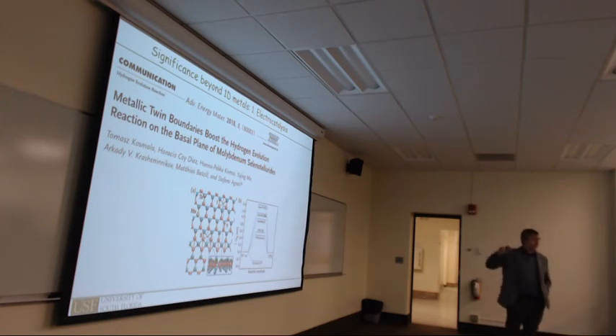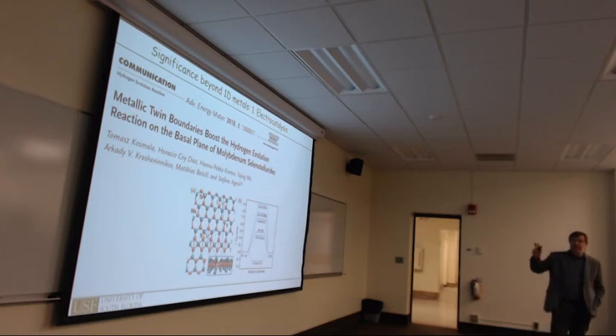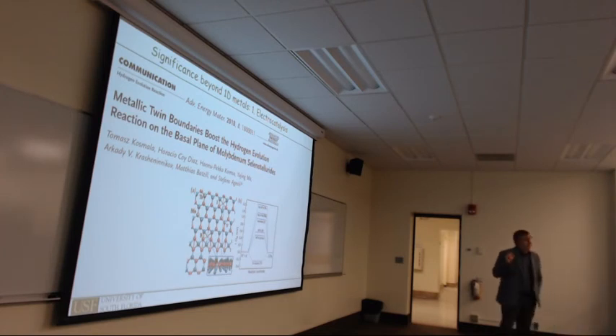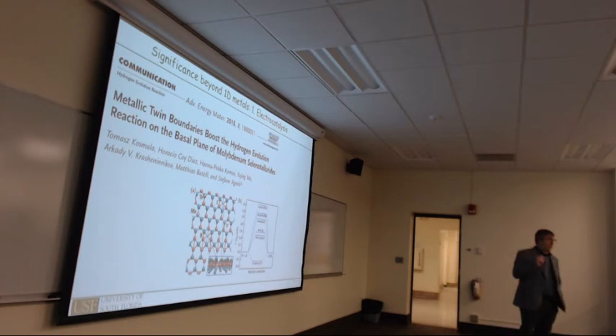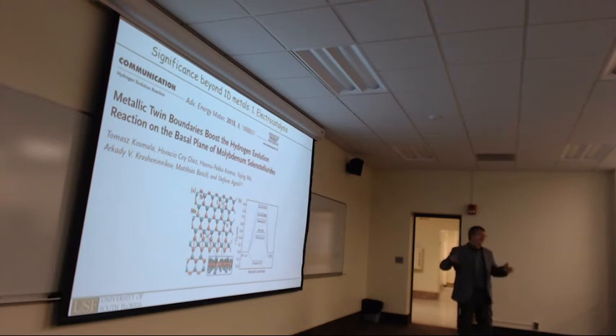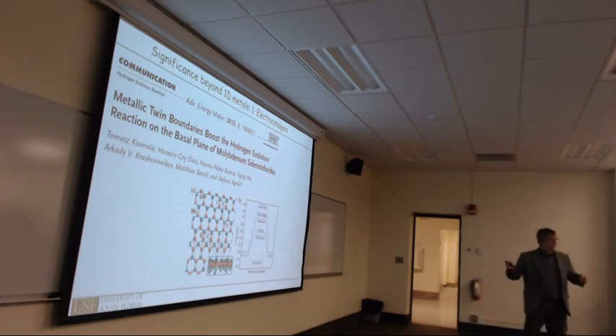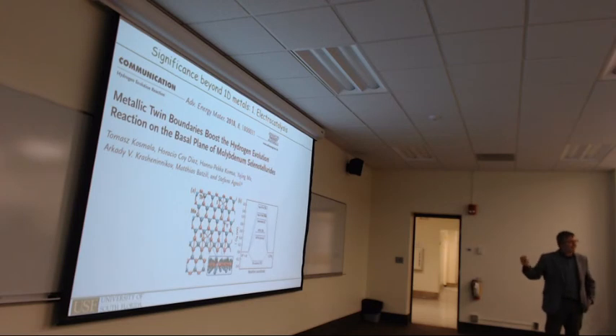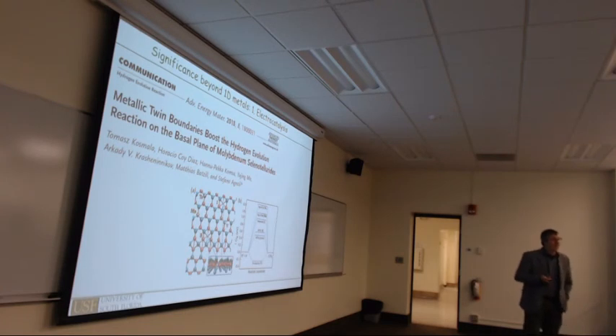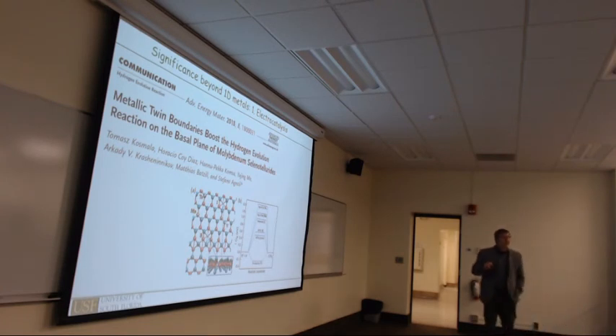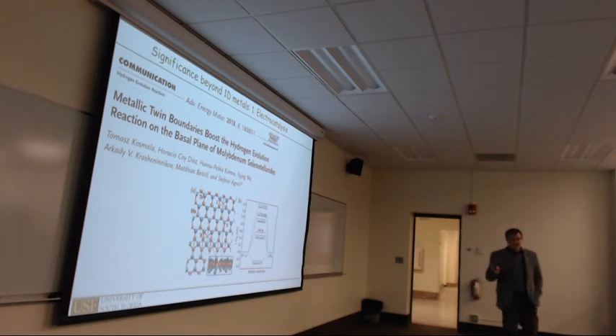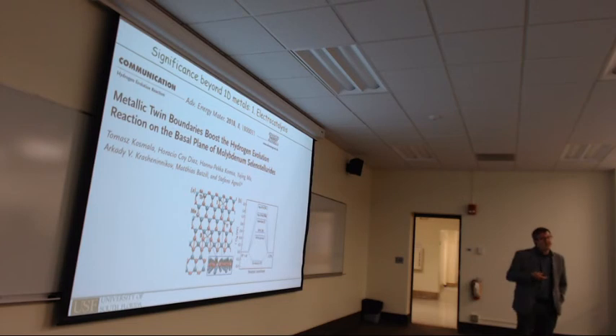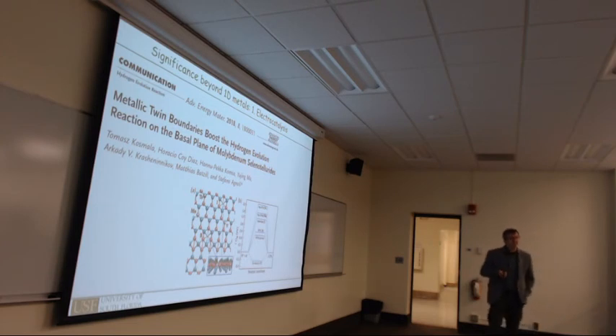Yeah, so I guess you can clean somewhat with the electrochemical cell. But they are fairly stable. The molybdenum selenide in particular is very stable. We took samples to the synchrotron in Paris. We specifically built a vacuum suitcase, which cost us thousands of dollars to ship to Paris. And we took the sample in air, and there was no difference. So they survived exposure to air very, very well, the molyselenide. But you get a carbon layer on it or something. You can heat it up in vacuum and clean it fairly well. So we didn't see much contamination on molyselenide.